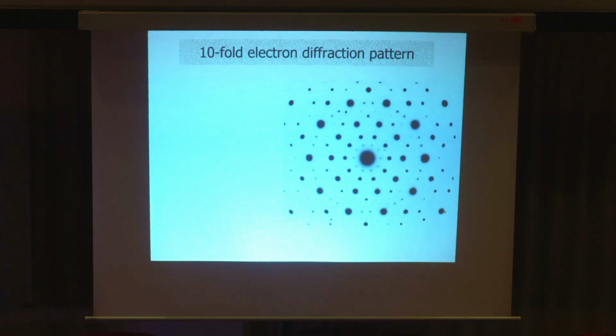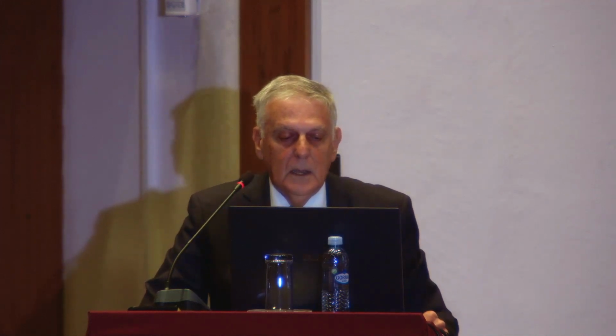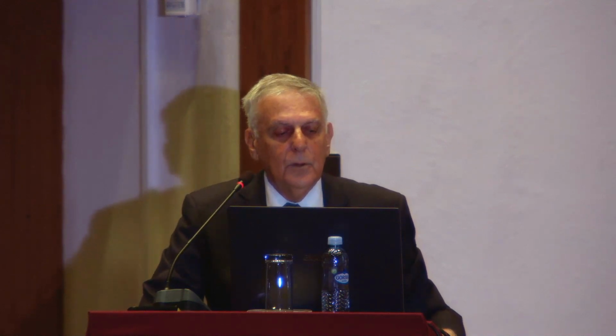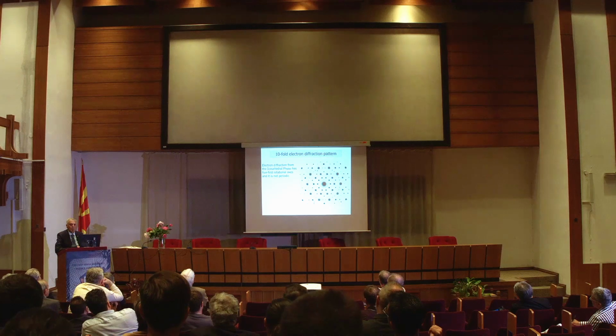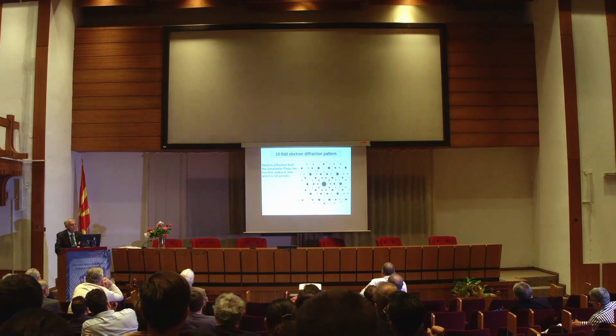So I look at the diffraction pattern and I say, well, what is the rotational symmetry? And I start counting, 1, 2, 3, 4, 5, 6, 7, 8, 9, 10, no, cannot be. And the other way, 1 to 10-fold, and I write in my logbook 10-fold rotational symmetry. And so this is electron diffraction from the icosahedral phase. I will explain why we called it icosahedral phase later on. And it has 5-fold rotation axis. It's not 10, it's 5-fold. But you could not tell from this very first experiment that it's really 5-fold.